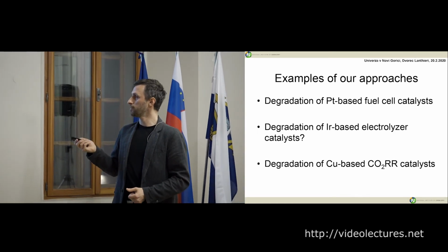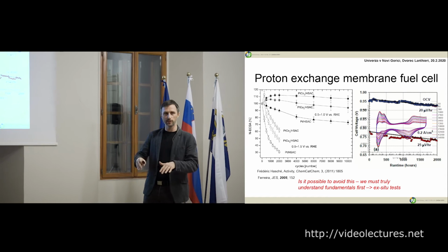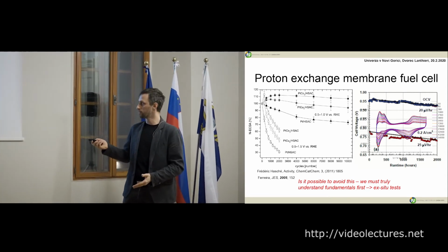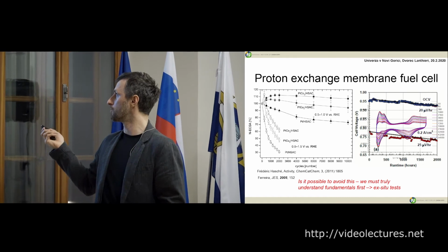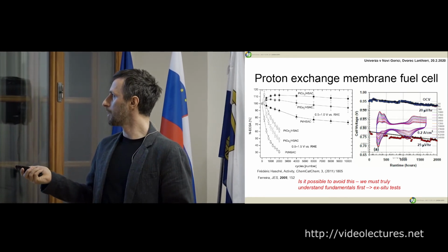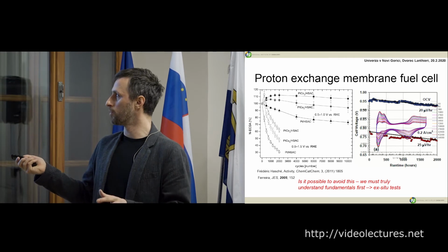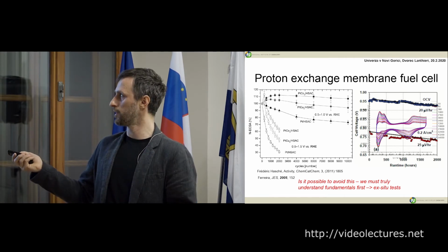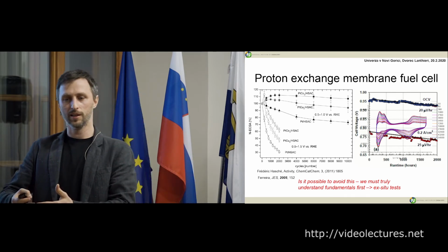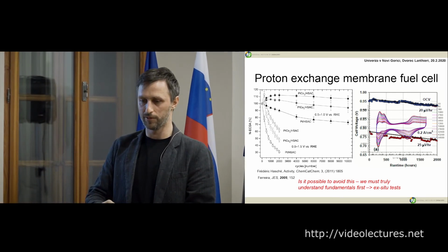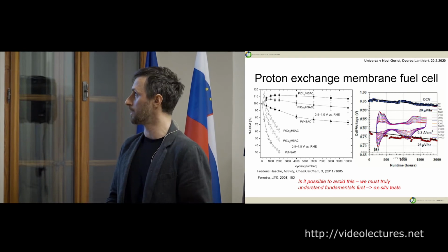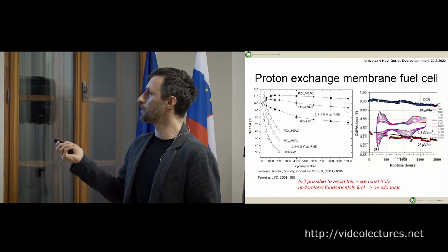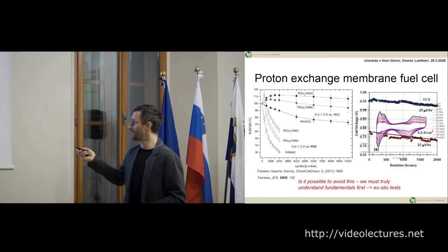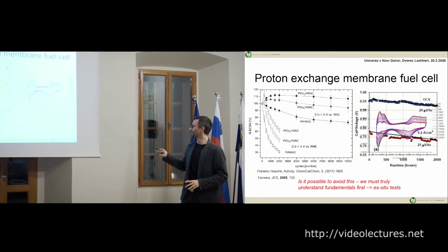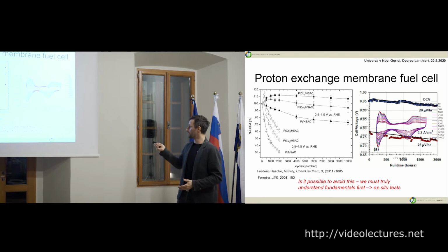In a proton exchange membrane, these curves should just tell you that we are losing activity. So it's not stable, with certain protocols we're losing power, we're losing surface area. It depends on which protocol you have. If you cycle to higher potentials, you're losing the surface area much faster. Surface area means activity practically, because if there's less surface area, there's less catalyst to run the reaction. Here is the typical CV. I said I would show one CV, and this is it, a cyclic voltammogram, and it's the only one. Here are the features of platinum, which are getting smaller, so it means you're losing the surface.